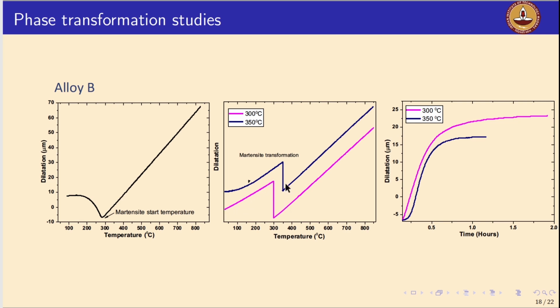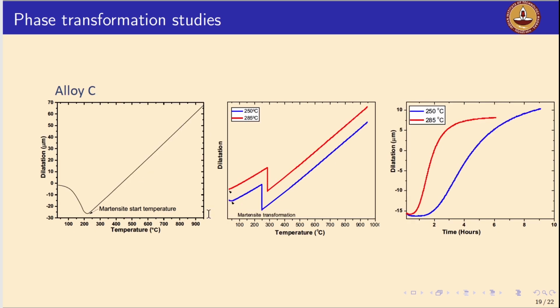Slightly increasing the temperature from 300 to 350, right, we found some martensite peak. That means that the microstructure of this thermal cycle would contain bainite, retained austenite, as well as martensite, right? So that may not be an ideal microstructure, because that may induce cold cracking when the martensite is present in significant volume fraction.